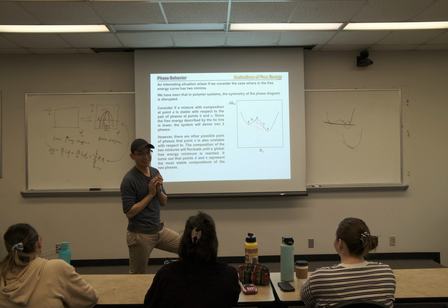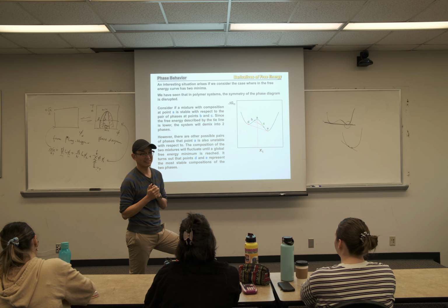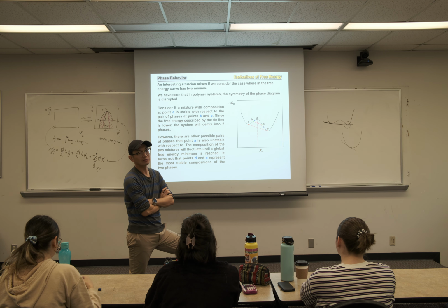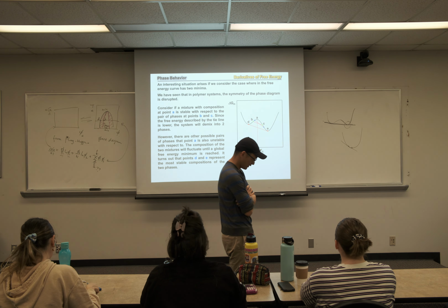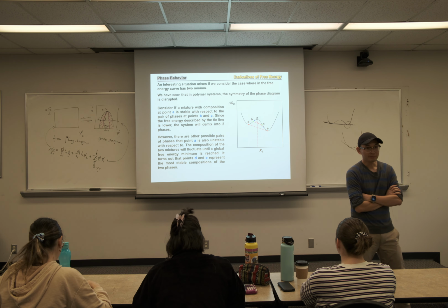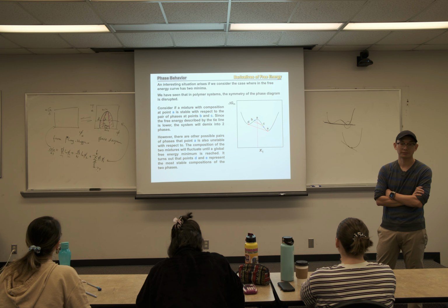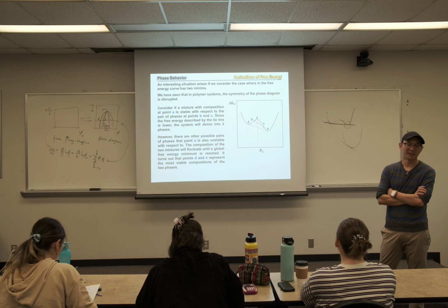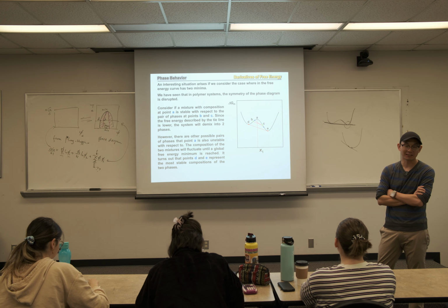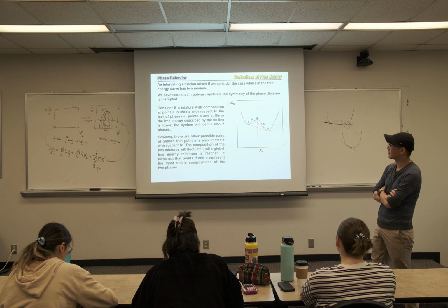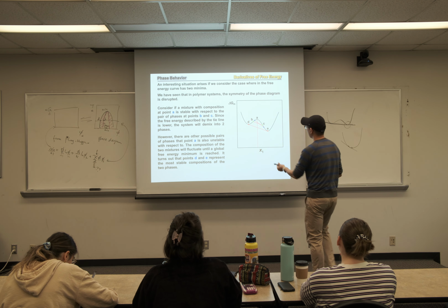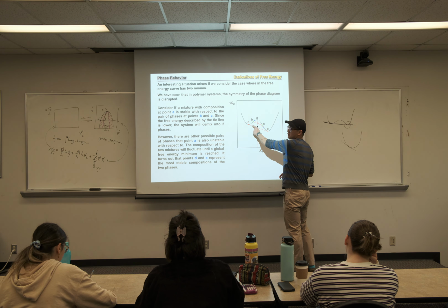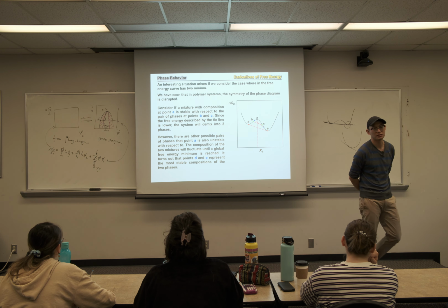Yeah, so is B the inflection point where you have the parabola going from concave up to concave down? Right, and that's correct. Anywhere in between that inflection point and the actual minimum at D is metastable. You can say it's minimum, but to be more accurate, it's a tangent line, which is the straight line cutting, when it's barely touching it. So this is not going to be exactly minimum, but close to the minimum.